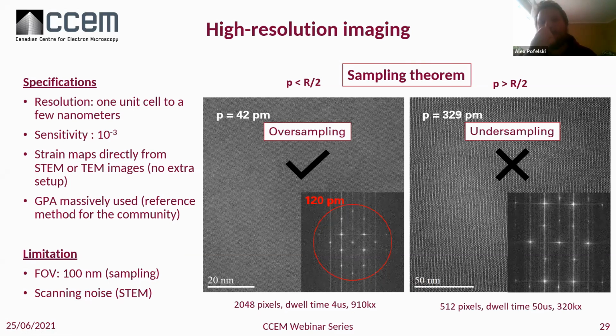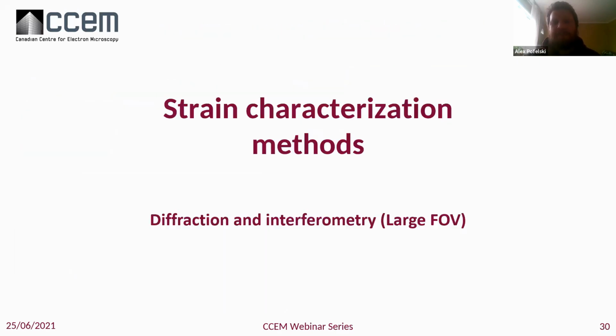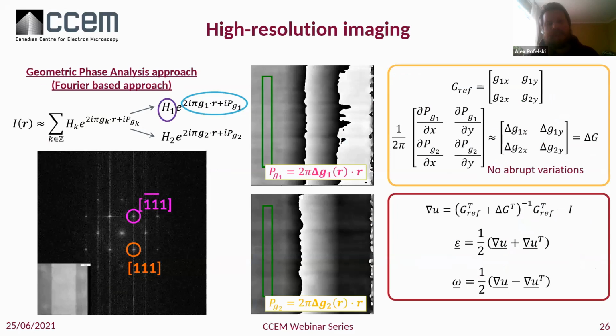That is true, there is this option in SmartAlign where you can actually rotate. Yes, I completely agree with that comment. It removes any biases regarding the scanning directions, which helps. I didn't go into the detail of the SmartAlign approach, but definitely this is a good idea too. And I would add also, to not have the atomic columns exactly aligned along one scanning axis, to tilt it a little bit off. Yes, definitely.